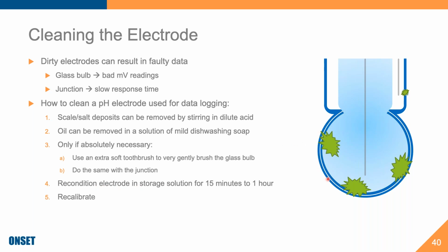And that's this layer again. Or if you've done something like dishwashing soap for an extended period of time, or you've brushed it with a toothbrush, or even if you've been logging in fresh water, then I would recommend reconditioning for a minimum of 15 minutes, or maybe even like an hour, and then overnight would be the best option for all of it. If you find yourself having to do that, then your best bet would be to have spare electrodes available when you go out to check on your logger, download the data, maintain the logger itself, the body of the logger. If you have a spare electrode, then you're able to just swap it out with a clean bulb that had been cleaned and reconditioned, and then recalibrate every time. Anytime you recondition your electrode, every time you clean your electrode, you should definitely recalibrate.